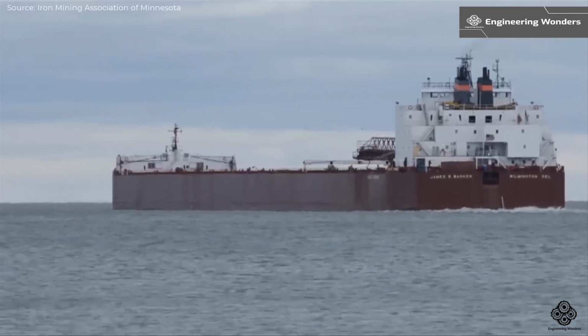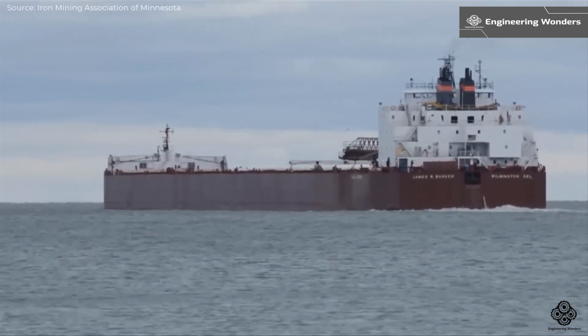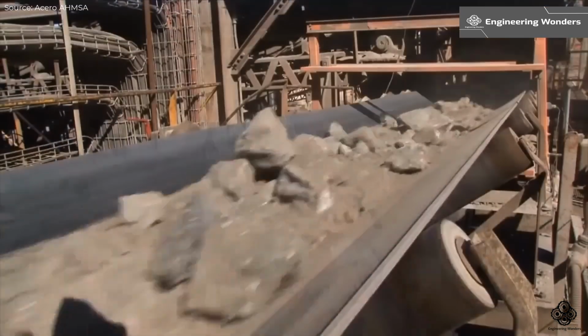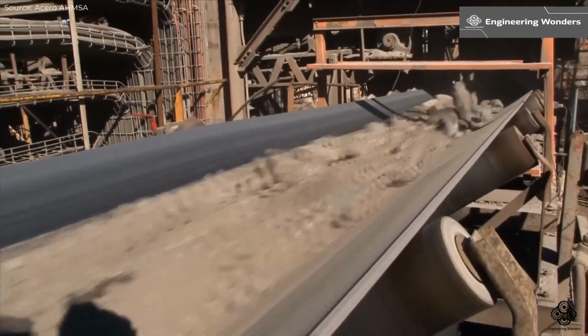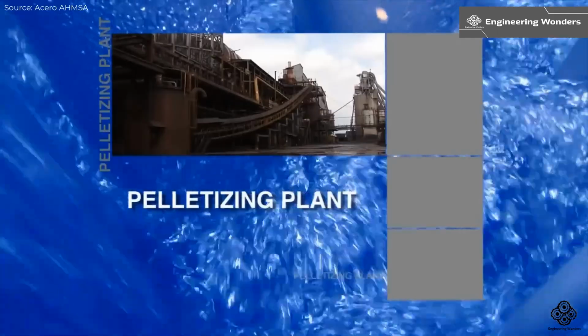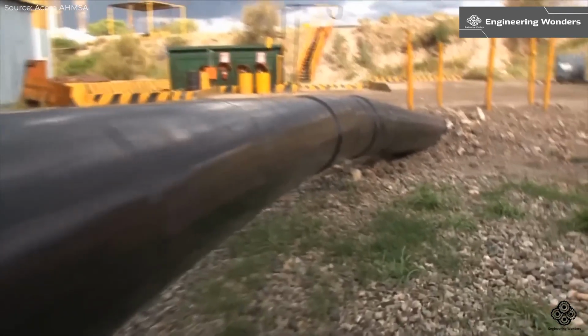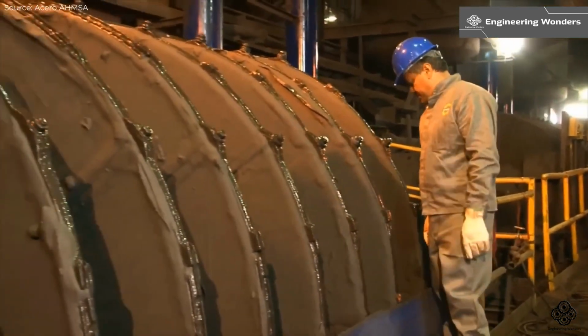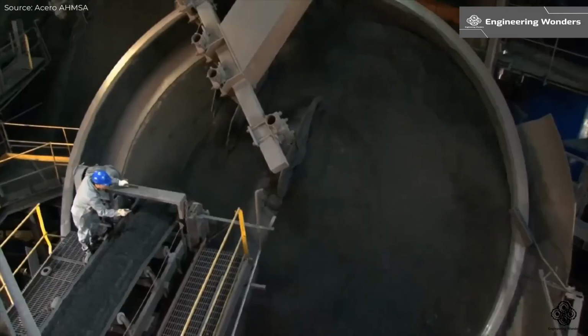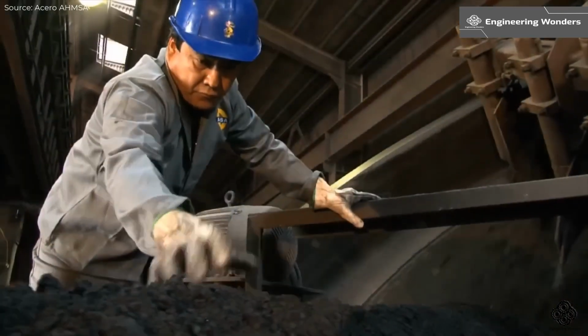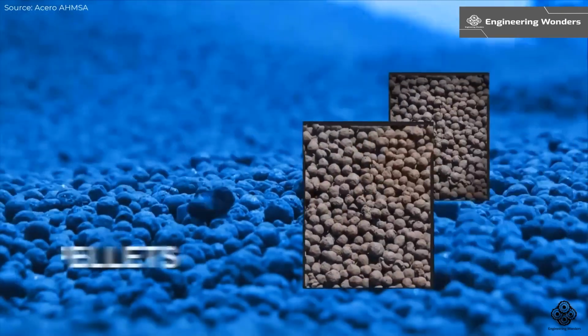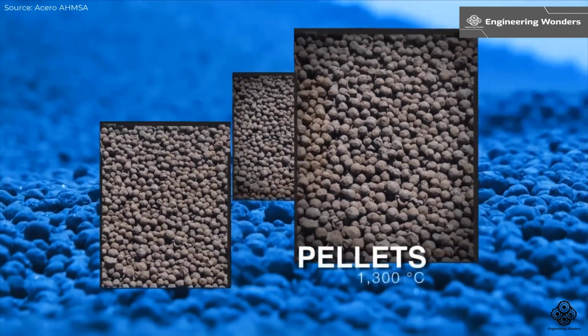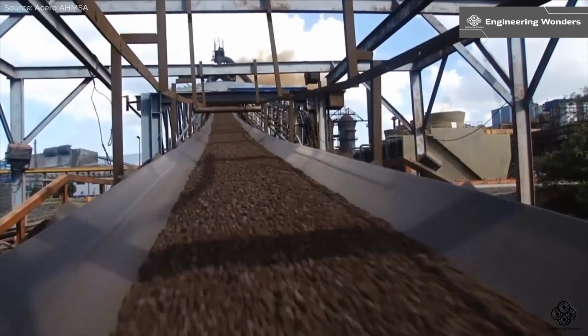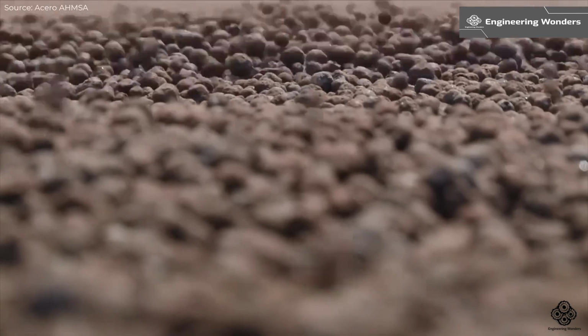Integral to our daily lives. Iron ore from the Hercules mines in the Coahuila Desert is transported as a slurry through a 14-inch diameter, 180-mile-long pipeline to the pelletizing plant. Upon arrival, the slurry is filtered to recover water, and the dry ore is then sent to pelletizer discs. Here, it is mixed with binding agents to form small balls called pellets. These pellets are heat-hardened at 1,300 degrees Celsius before being sent to blast furnaces.